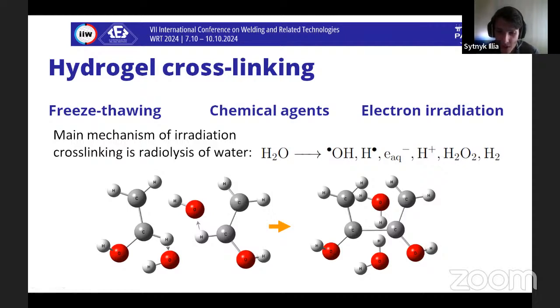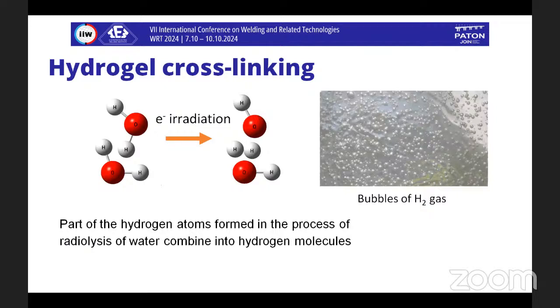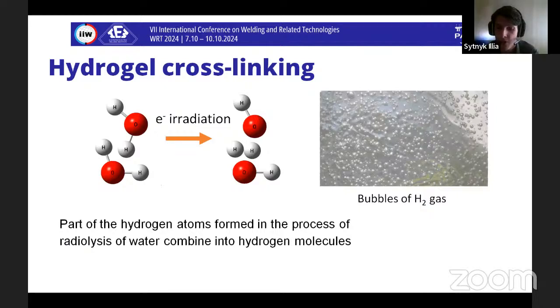The radicals created through this mechanism form bonds with other parts of the same polymer macromolecule or with other macromolecules. Part of the hydrogen atoms formed in the process of radiolysis of water combine into hydrogen molecules, forming gas bubbles ranging from 0.2 millimeters to 2 millimeters in size in a sample's volume. Their size and concentration correlate with radiation dose. In the context of use of hydrogel for medical purposes, radiation has an effect on ease of use, which is mechanical properties, and functional efficiency, which is ability to absorb moisture, or in other words, hydrophilicity.